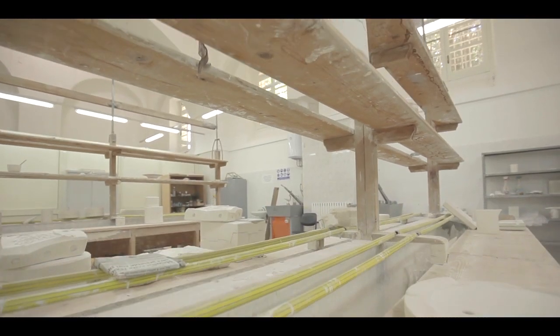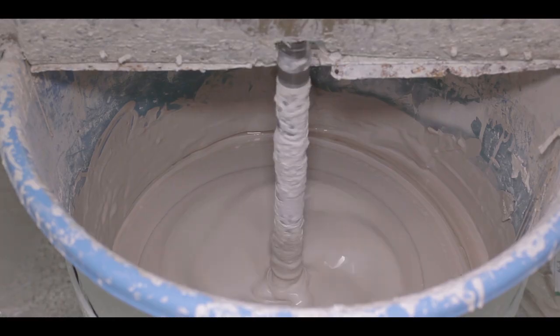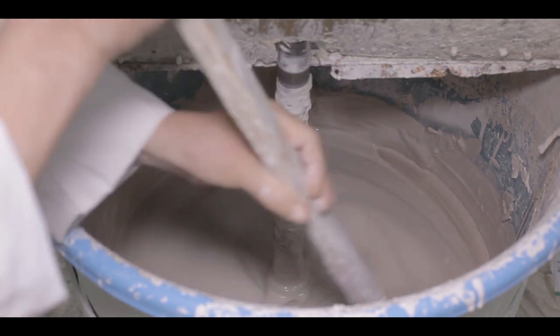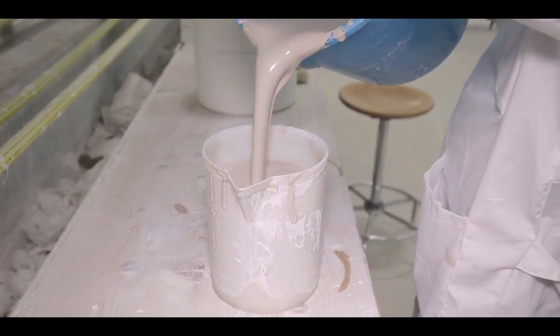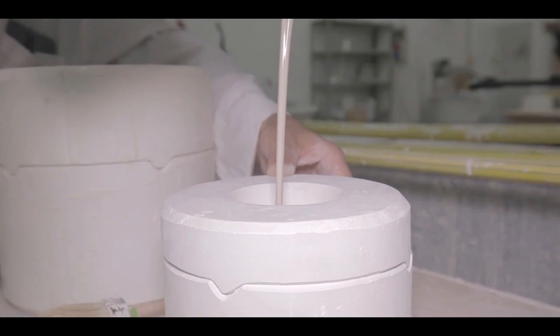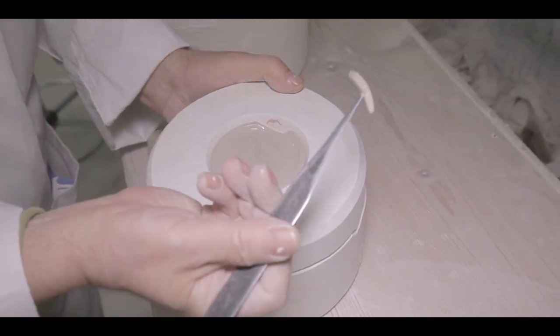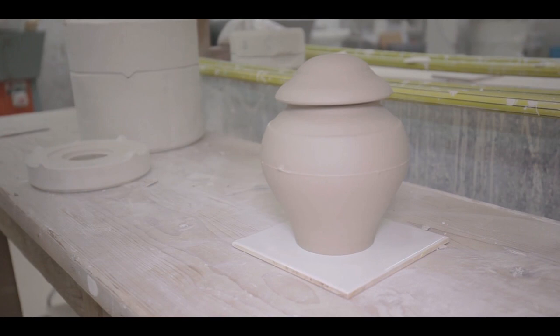The project phase is the first and very important step for the realization of a ceramic piece. During the project, we need to take care of the nature of the material and the fact that in firing, ceramic materials — in particular porcelain — undergo notable dimensional variations. The soft porcelain clay body has a shrinkage ranging from 12% to 18%. Therefore the designer must produce, in addition to the drawing of the fired piece, also the drawing of the unfired piece — applying the so-called enlargements to produce the working sheet.